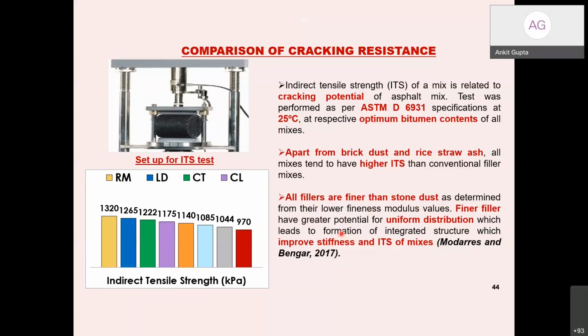So all fillers are finer than the stone dust, as determined from their lower fineness modulus values. And the finer fillers, as I told earlier also, have a greater potential for uniform distribution, which leads to formation of a good, compact structure, which improves the stiffness and the ITS of the mixes. So most of the fillers are showing superior properties for cracking resistance also.